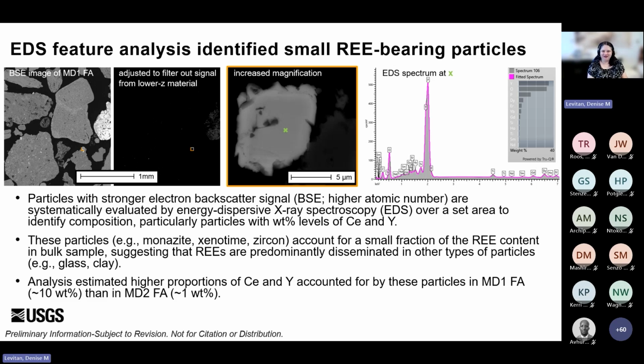And we can estimate, and I want to emphasize this is an estimate because some particles are really too small to quantify, what fraction of our total area these rare earth element rich particles account for. So we looked at an area of this sample for cerium and in these bright particles. And what we found is that these distinct independent particles accounted for maybe about 10% of the MD1 fly ash sample and only about 1% of the MD2 fly ash sample.